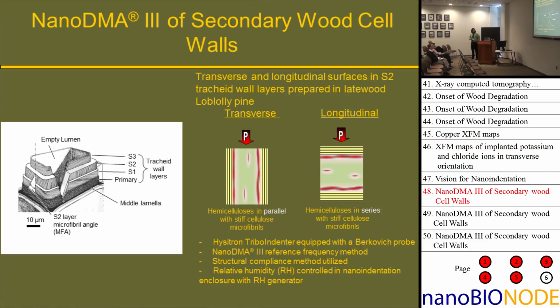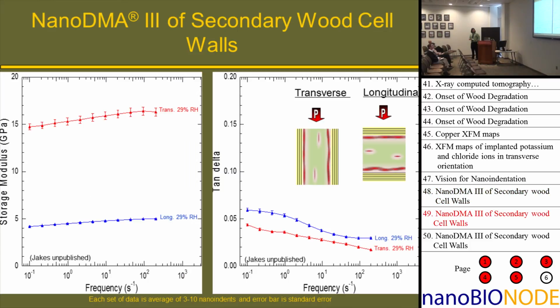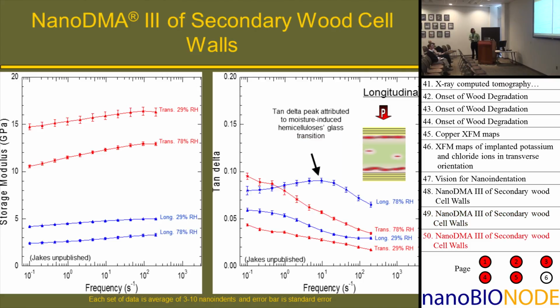And then getting back to our nanoindentation, you can test the cell wall in the transverse plane and the longitudinal plane, and what we actually find is that if you do this at different humidities, when you're testing in a direction that's perpendicular to the elementary fibrils, so you've got these softened regions of hemicelluloses, you do actually get a peak that shows up in the tan delta, and we believe that this peak corresponds to the moisture-induced glass transition inside of the wood cell walls.